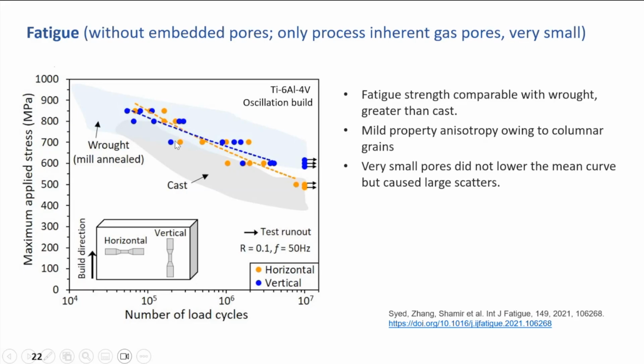The message I want to show is that the gray part is the traditional cast titanium 6-4. The pale blue shadow is the wrought, mill annealed. Then the blue and the orange dots are the additively manufactured, either in vertical direction or horizontal direction. The message to take home is fatigue strength is really okay. It's comparable with the wrought or even greater than the cast.